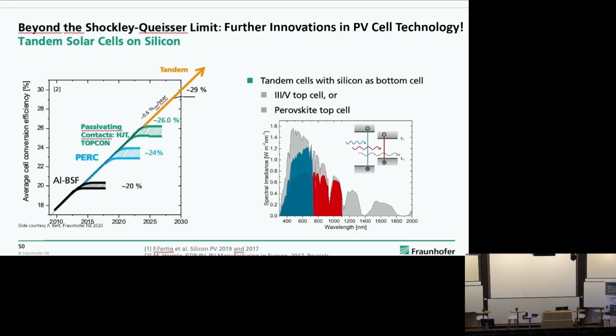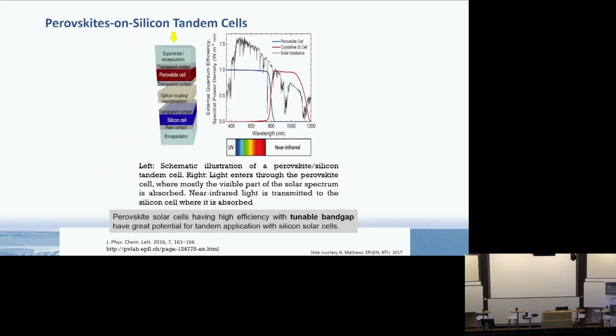Tandem cells where a good silicon solar cell on the bottom can provide the first 25% of efficiency, but we add a top cell which has a wider band gap so that the light for the silicon cell still is transparent, but you can create additional carriers with a higher band gap, and therefore you can shift the efficiency beyond the Shockley-Queisser limit. Whether III-V top cells, where we would have to develop low-cost III-V deposition technology, or whether perovskite top cells, or maybe even II-VI top cells will at the end of the day be the winning technology, we don't know yet. But in any case, we can say very exciting technology developments are still going on in silicon cell technology.